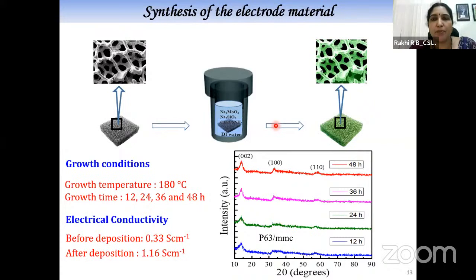We collected all the samples after hydrothermal growth. On the three-dimensional substrate, we directly grew these MoS2 nanostructures at different growth times. And in each case, we collected the sample grown on the nickel foam substrate, as well as there was some deposit in the autoclave itself, that is, without any substrate. The MoS2 nanostructures formed inside, that also we have collected, and we characterized the sample.